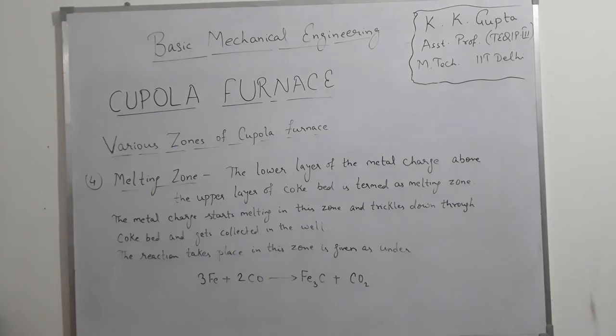Fourth zone is melting zone. The lower layer of the metal charge above the upper layer of the coke bed is termed as melting zone. The metal charge starts melting in this zone and trickles down through the coke bed and gets collected in the well. The reaction that takes place in this zone is given as: iron plus carbon monoxide gives iron carbide plus carbon dioxide. It means 3Fe plus 2CO gives Fe3C plus CO2.